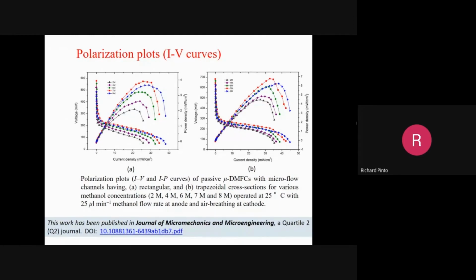The left side figure is obtained for rectangular channels. The right side is for trapezoidal cross-section channels, for various methanol concentrations. Of course, it increases with higher methanol concentration; methanol is diluted with water. The highest is obtained for 7 molar. At 8 molar it drops because of oversaturation. Here also, 7 molar concentration gives the best results, even for the trapezoid.